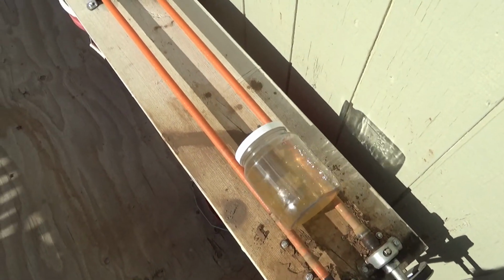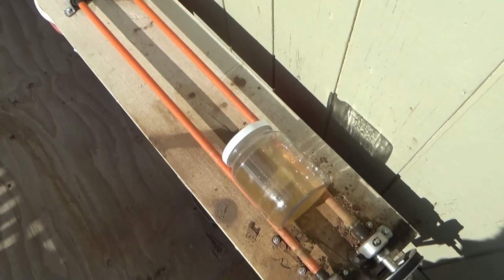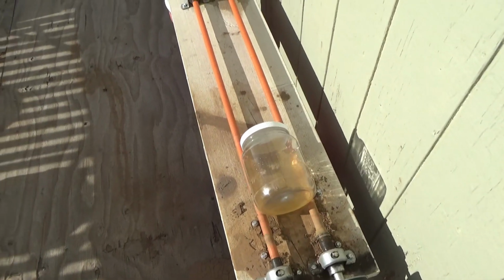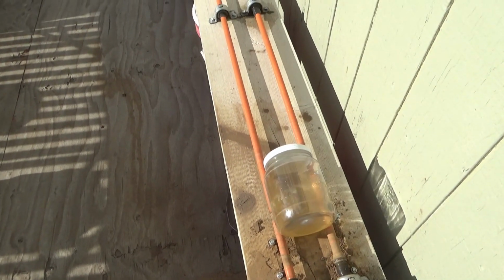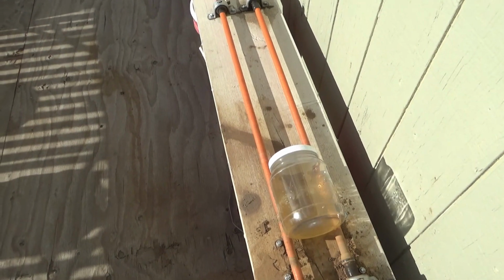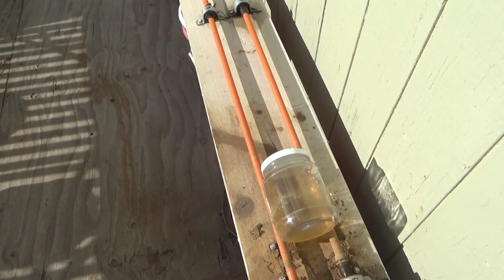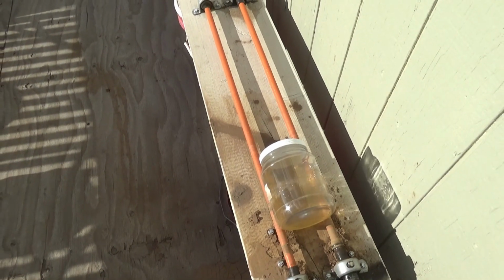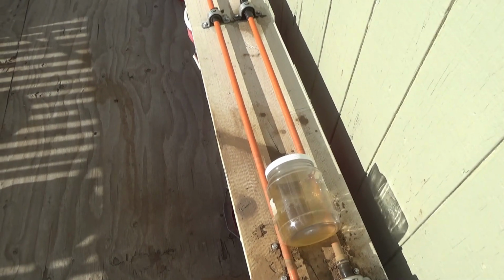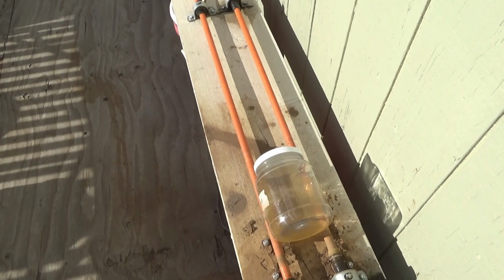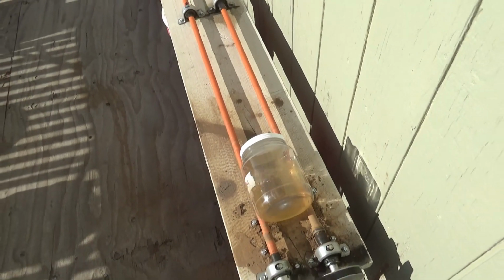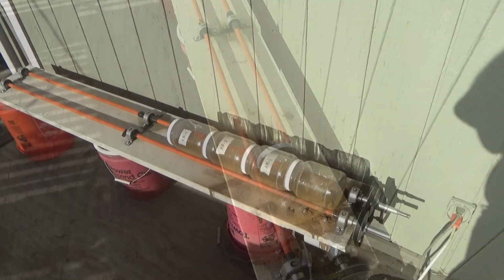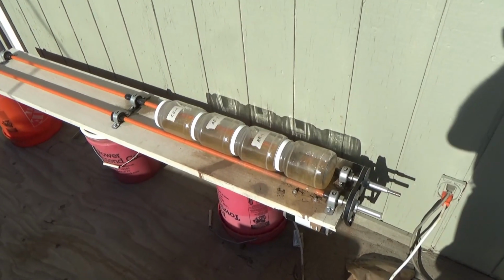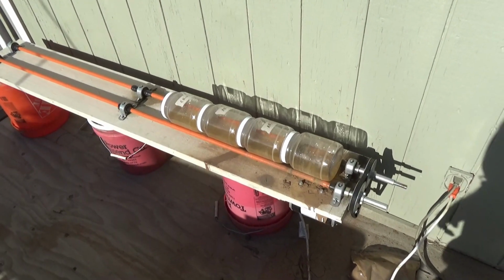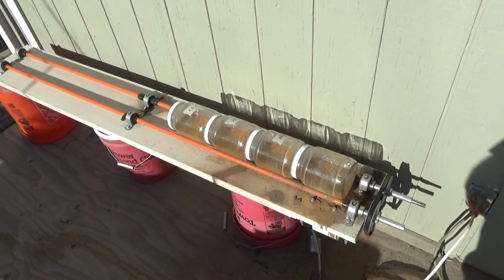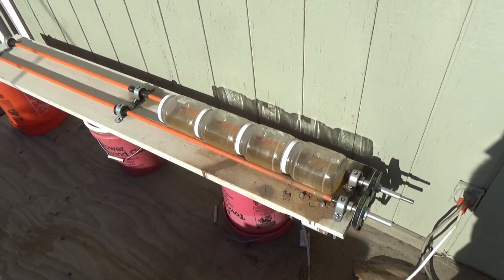The idea is 1 hour bottle roll is more contact time than we're ever going to be able to practically use. That should be less resin than would normally work. So we shall see what we shall see. I expect to have residual gold in solution in each one of these things, which will give me my loading factor, but we shall see what happens at the end of an hour and then the laboratory tests. So there they are, all rolling. I staged them 5 minutes apart, which will give me time to take it out, get my sample, get the next one without changing the time that each one had to do its thing.